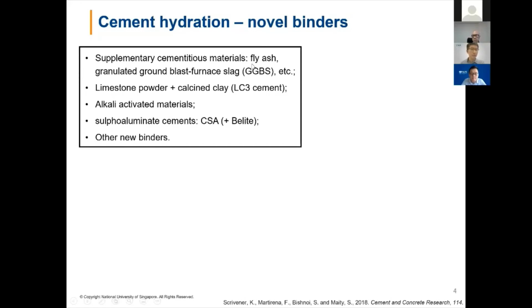And in recent years, there are other very hotly studied cementitious systems, such as the limestone powder plus the calcined clay system. We call it LC3 cement. And also the alkaline activated materials is very popular these recent years. And also the sulfoaluminate cements with or without belite phases, and many other new binding systems.